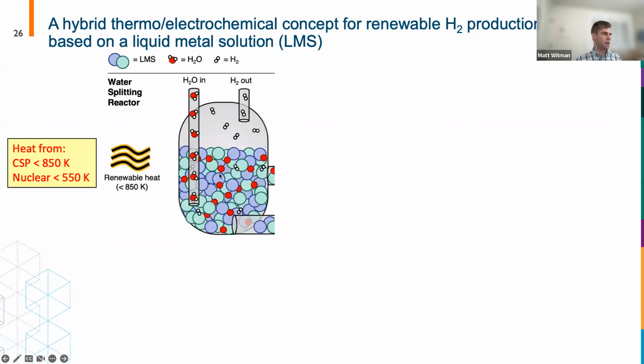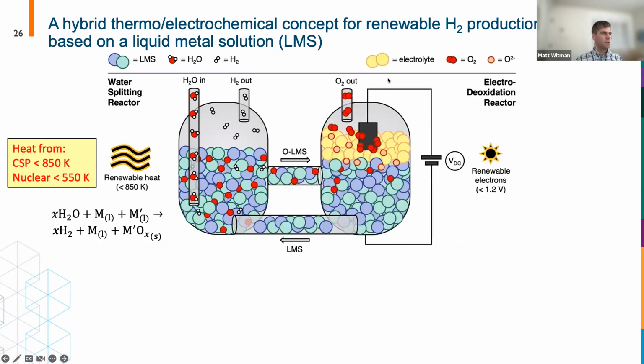So the way you would do this is with a liquid metal solution where you sparge in steam, and then you oxidize a liquid metal melt to produce hydrogen. And then in order to regenerate the liquid melt, you would do this electrochemical reduction of your oxidized liquid metal to liberate oxygen and refresh the liquid metal melt. And the goal would be to hopefully do this at a potential less than is required for typical electrolysis today. And this is the thing that Boston Metal is working on for direct iron reduction, same technology, but this would just be applied to the liquid metals that we're studying in this problem.